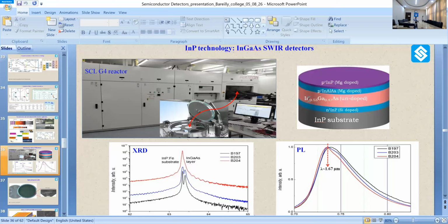Let's say 53% of indium is the only composition lattice matched to the indium phosphide substrate, so as to ensure defect-free growth on the indium phosphide substrate. For that, we use this kind of MOCVD reactor, where we grow this kind of material at 800 degrees centigrade to 1000 degrees centigrade. Okay, and you can see how we actually grow P-type and N-type material. It's basically in situ, epitaxially we can incorporate the dopants. Like in silicon, we implant arsenic, phosphorus, or boron for the N-type and P-type on a particular region of the silicon. But here, we actually grow the N-type and P-type material epitaxially, in situ.